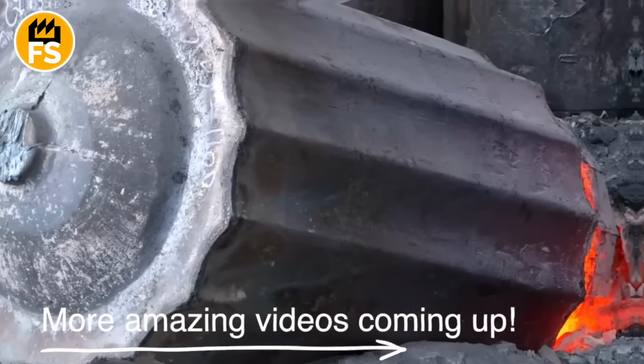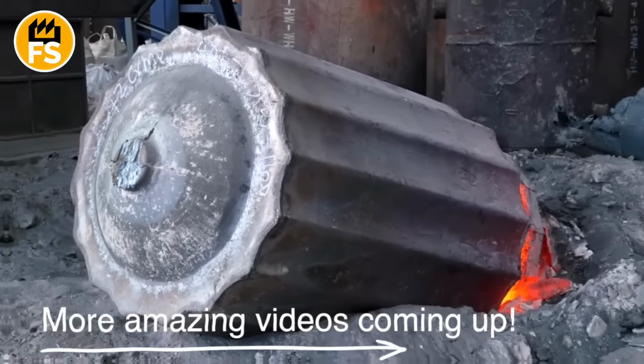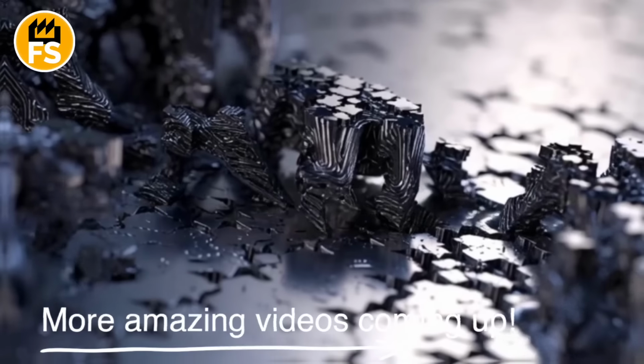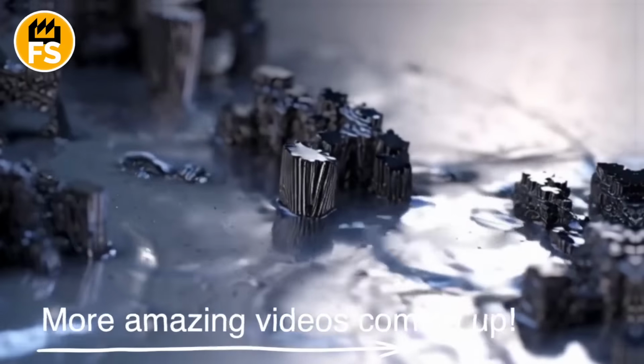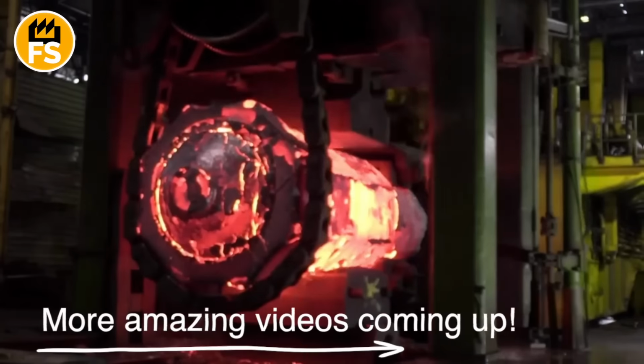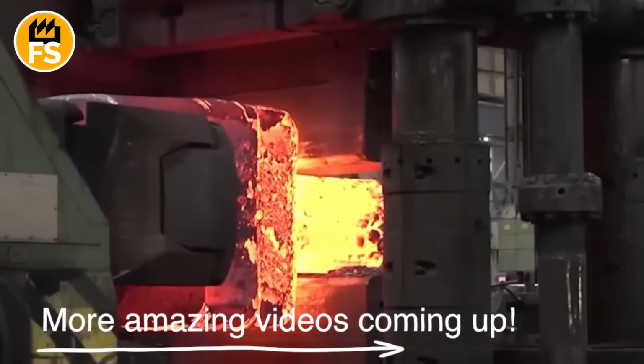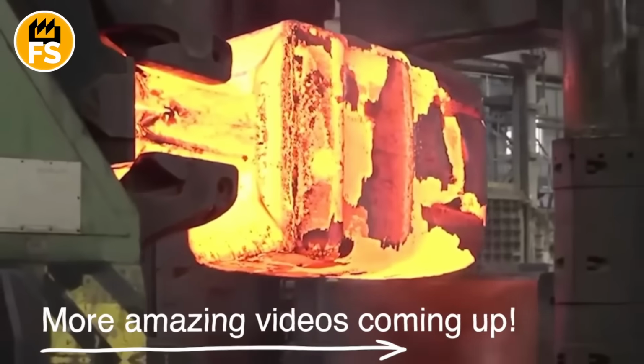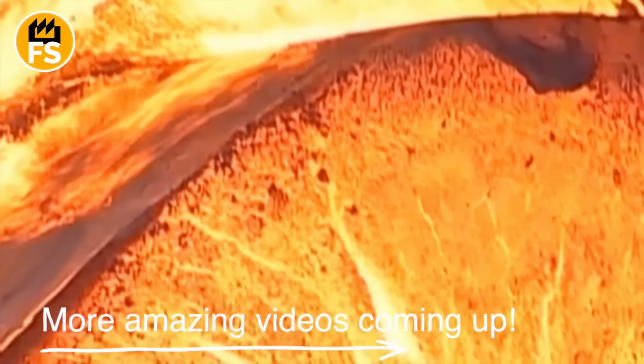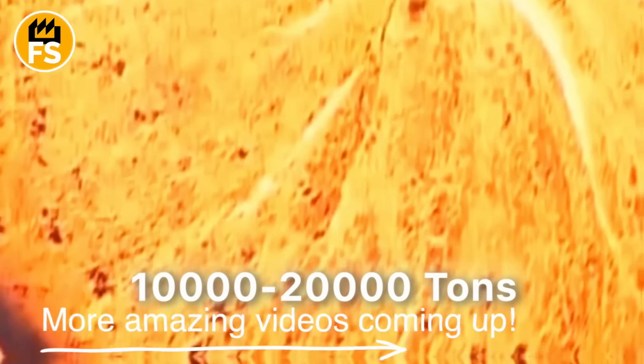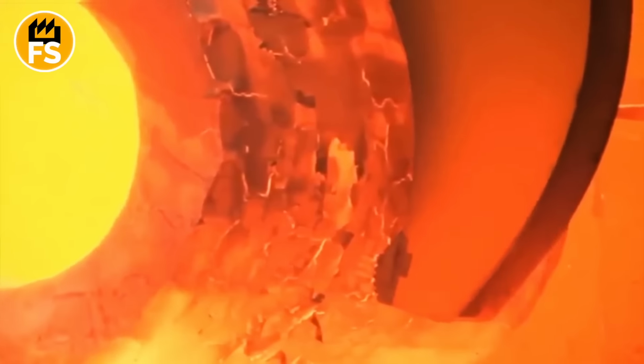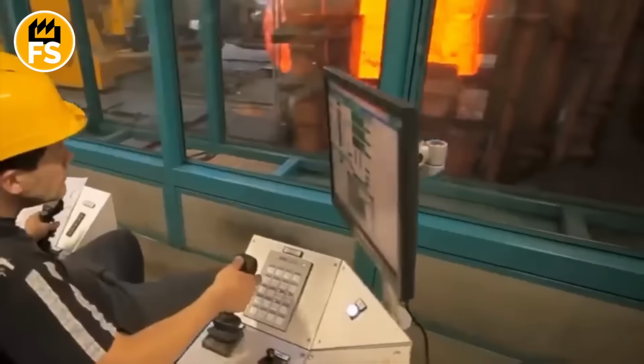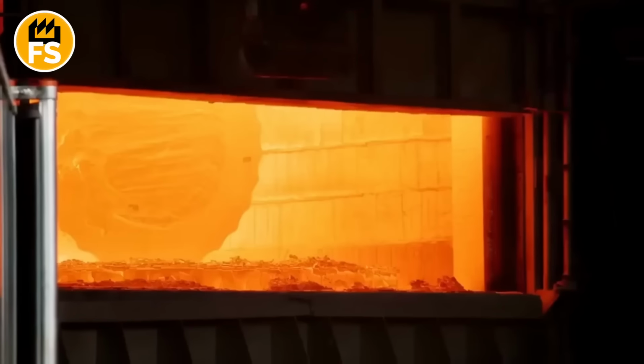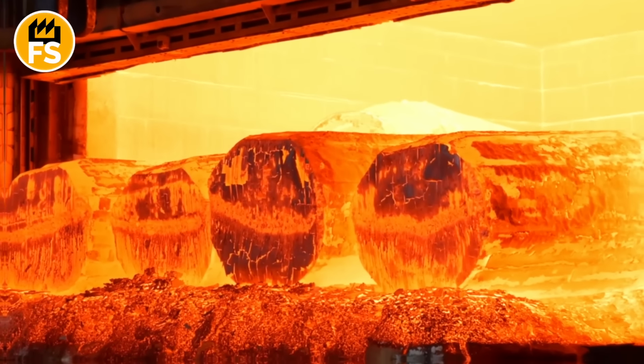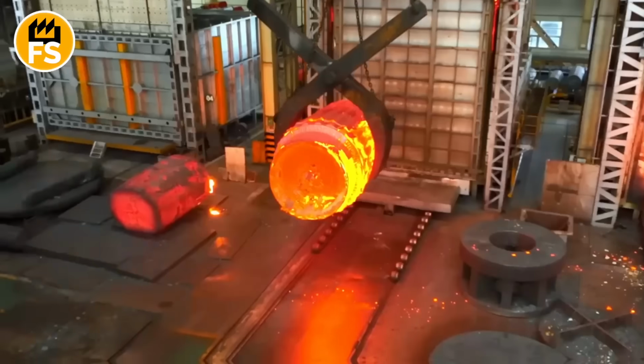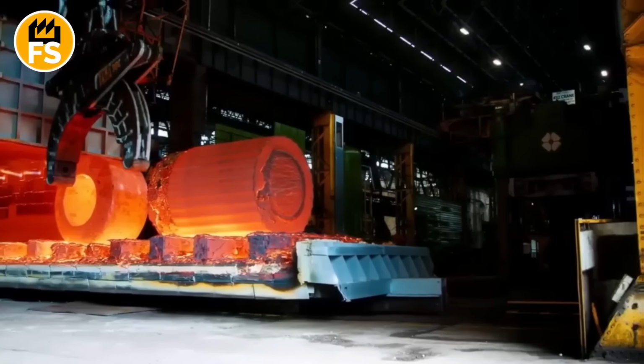The extracted ingot, despite its weight, is not yet a finished blank. It has a cast, coarse structure with large crystals. To transform it into strong, homogeneous metal capable of withstanding extreme loads, forging is required. Forging 500-ton ingots demands hydraulic presses with working forces ranging from 10,000 to 20,000 tons. For example, forging the largest reactor components requires presses with a capacity of 40,000 tons. Before forging, the ingot is again carefully heated in specialized furnaces. This process can take weeks to guarantee uniform heating throughout the entire volume of metal.